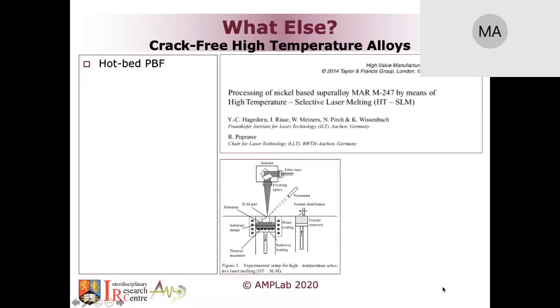Essentially, that machine can heat up to 1200 degrees Celsius, which is very high. The heat is provided by inductive heating, as you can see at the bottom there. It has cooling water around the chamber to stop the heat from getting out.